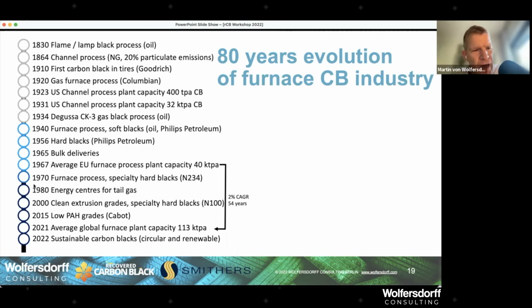And then, really surprisingly, the energy recovery, so the conversion of the excess methane gas into heat and, of course, carbon dioxide, only came in 1980. And these energy centers really make the difference in the plant efficiency and also in the carbon footprint, between 5 tons per ton of carbon black and 2.5 tons per ton of carbon black. 2000 came clean extrusion grades, so extrusion, especially body sealing profiles for cars, where the surface has to be really, really smooth, and also non-conductive, because modern cars now are made of steel, aluminum, magnesium, different metals that could corrode if they are in touch with each other.